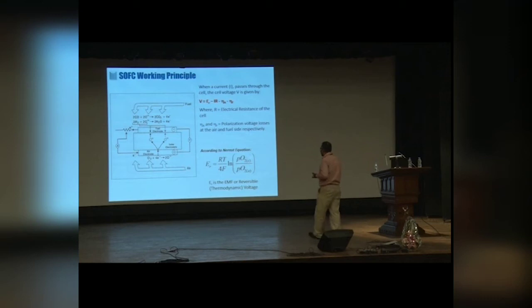You know that there is a very famous Nernst equation where if you have two oxygen partial pressures, I was talking about air on one side and hydrogen on the other side. That means you have two different oxygen partial pressures, and R, T and F are constants. Our electrolyte can give oxygen ion conduction only at high temperature, so if you keep it at a high temperature, that is the T, and R and F are constant, and if you have hydrogen on one side and oxygen on the other, naturally you will get some voltage. That voltage is called open circuit voltage.